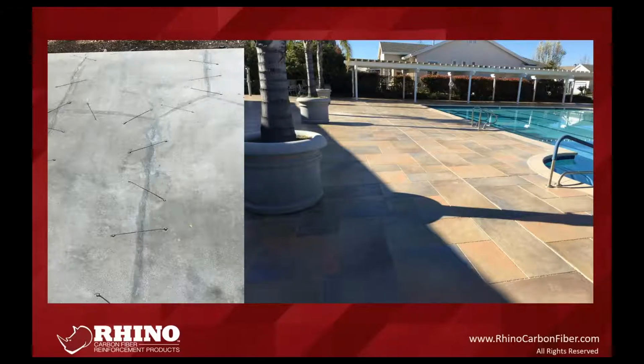And here's a couple examples. So this was out in California. Obviously, it was a large community pool here. Pretty severe cracking, but what's cool about this is after the fact, they did a decorative coating or decorative overlay, and this was actually stamped concrete with an artisanal finish. They bring a guy in who does a phenomenal job. A lot of this is going to be hand applied as far as the actual coloring goes of the concrete, the staining of the concrete. But this is the beauty of the repair itself, is you can't tell it's there after the fact.